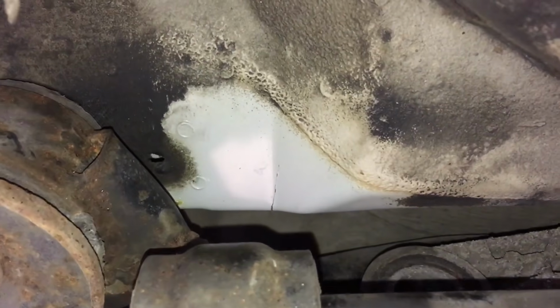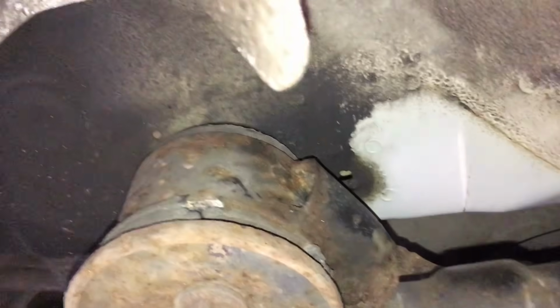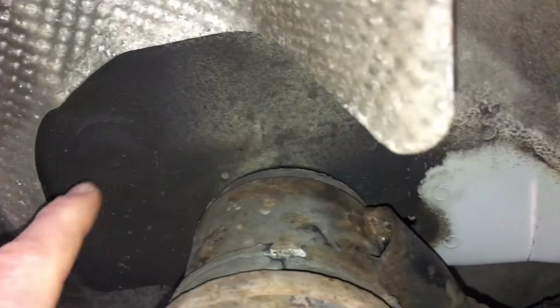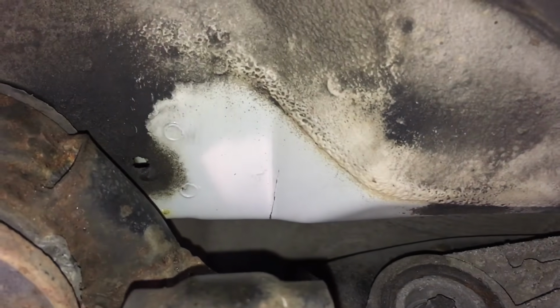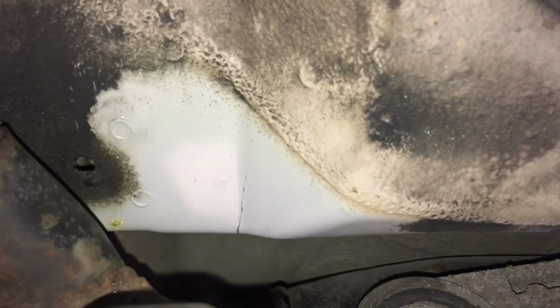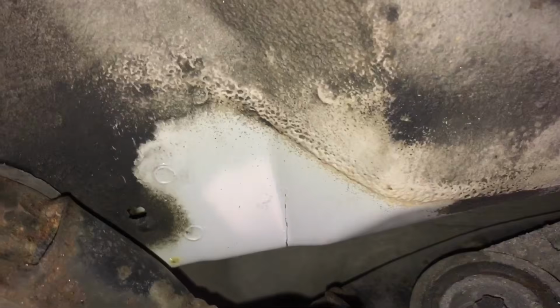But unfortunately, they hadn't cleaned the rear axle carrier panel like we do, and like you should, because the undersides of the cars always suffer with grime and build up of dirt, road dirt. That's what the car looks like underneath if you clean all that off. And when you do clean it off, you can then quite clearly see a hairline crack. Those aren't terrible, they're only hairline cracks, but it is quite long, because that there is nearly 50 millimeters long going that way, which is horizontal, and then when we go around the 90-degree corner and go up the vertical slope, the crack is also travelling and goes very high.